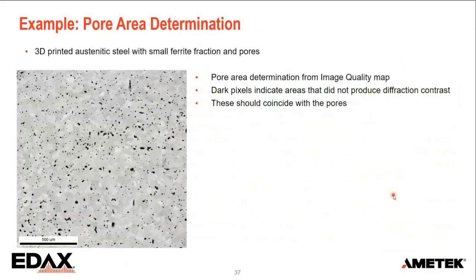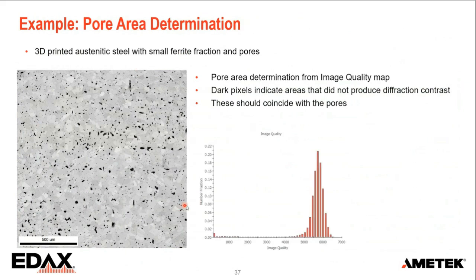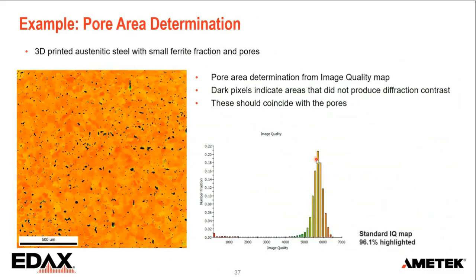Now, then porosity. You can do a lot of stuff there as well. So here I have a 3D printed steel. There's a little bit of ferrite, a lot of porosity. And we can use the image quality map, just looking at all the bad points, so very dark here. And that gives me, with highlighting, so there I link my data sets again, I go from 96.1% highlighted, so about 3.9% could be pores.